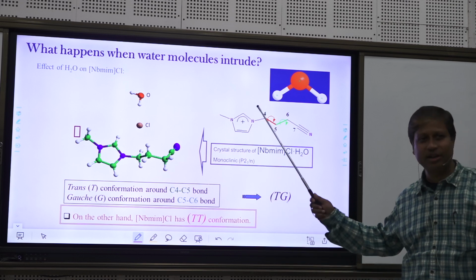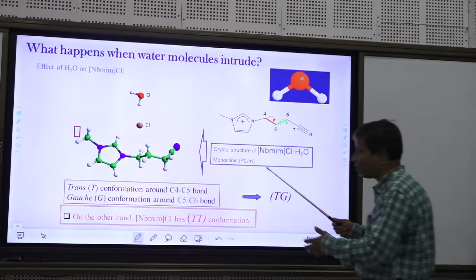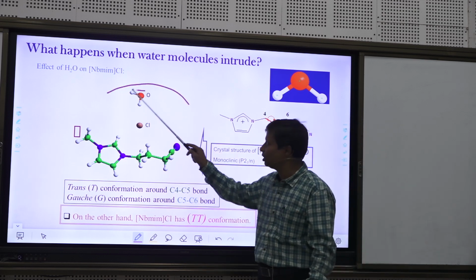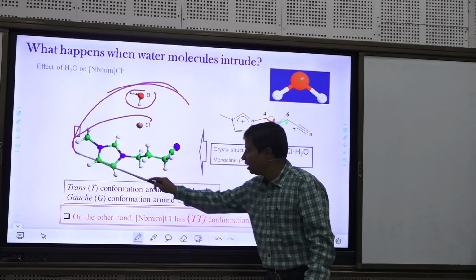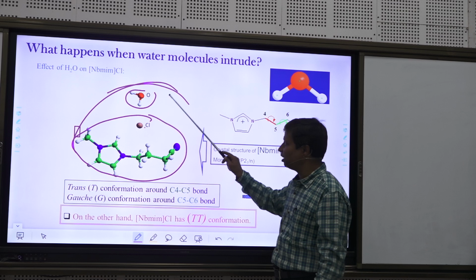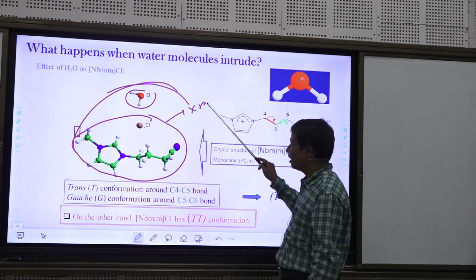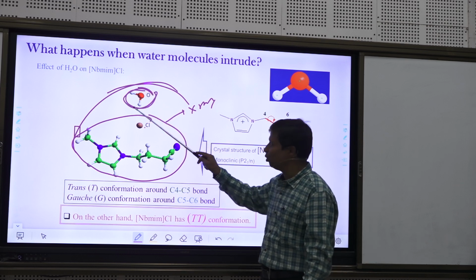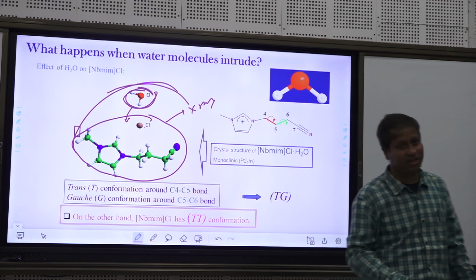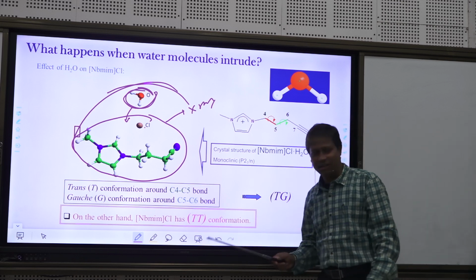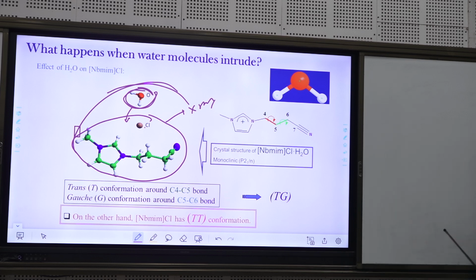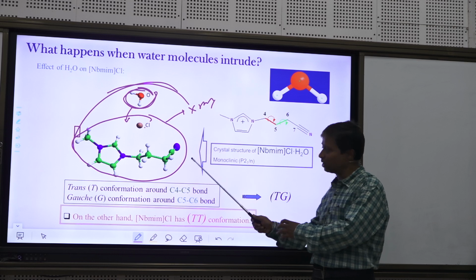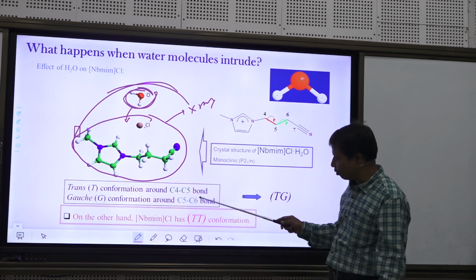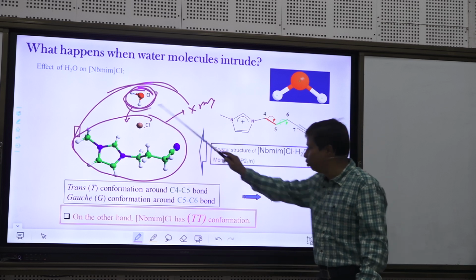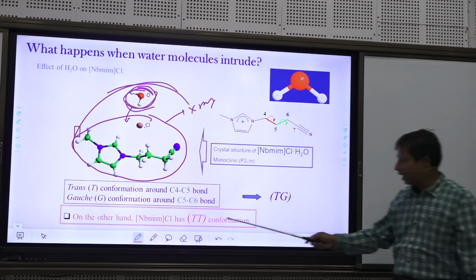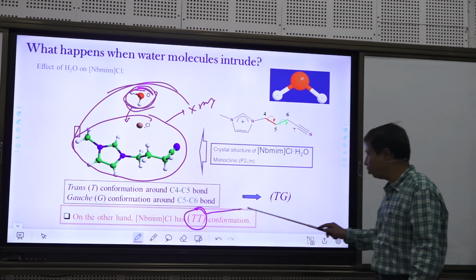But in this case, it was good luck that I obtained a crystal in which there is a water molecule. This is a water molecule. So this is a cation-anion combination whose X-ray structure I have, and when the water molecule is included, in that case also I have the X-ray structure. So now I have the information on the exact conformation from the X-ray studies, and I have the information from the Raman studies on what the marker bands are. Then it is found that because of this water molecule inclusion, there is a change in the conformation from trans-trans to trans-gauche.